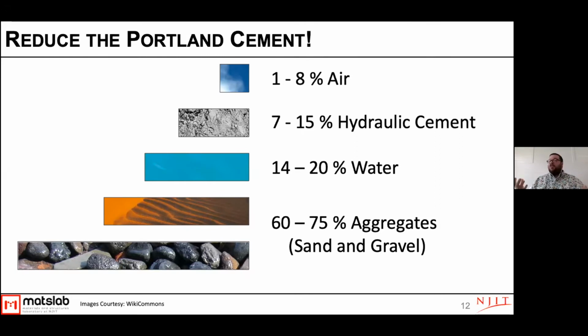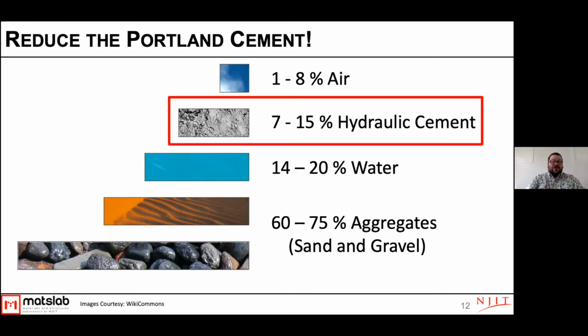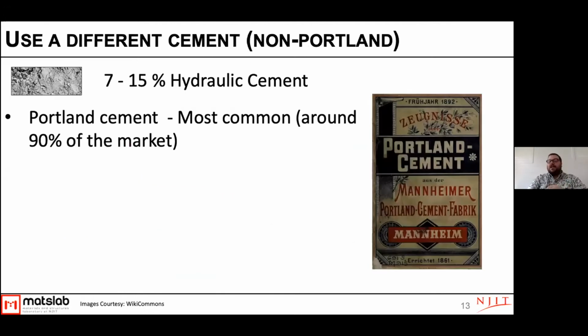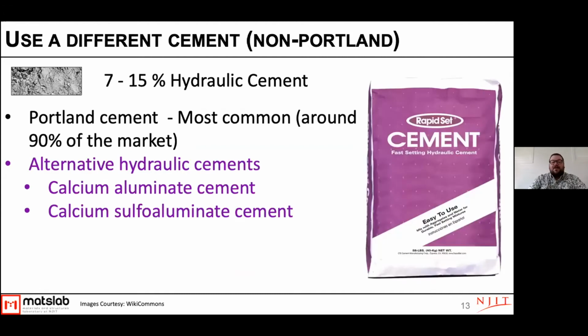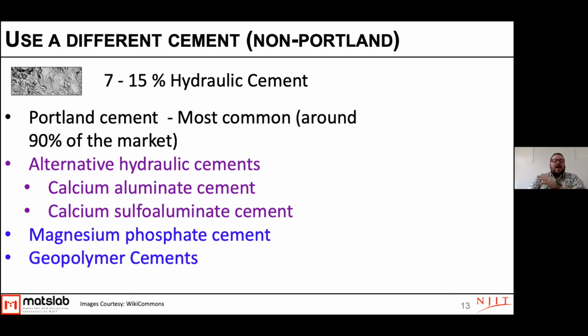Other materials, like we can make great cements out of phosphates, but we need all the phosphates that we make to use as fertilizer. And there's no way that the phosphate supply, even if we weren't using it as fertilizer, could supplement what we need for cement. So our first task is to try to reduce this amount. Portland cement is what we mostly use. This is around 90% of the market. We also have some of these alternative cements, like calcium aluminate cement or calcium sulfoaluminate cement. They're similar in composition to Portland cement. And then we have these newer systems, magnesium phosphates, which again are very expensive and we can't produce a lot of, and geopolymers, which are difficult to work with, but coming on more, and those use non-Portland cement materials.